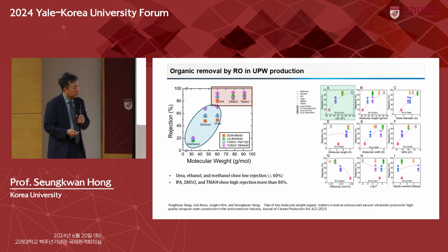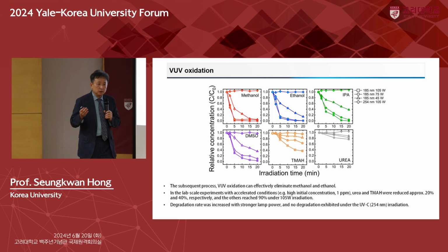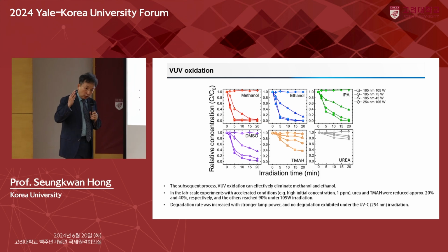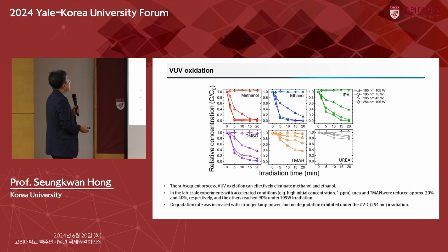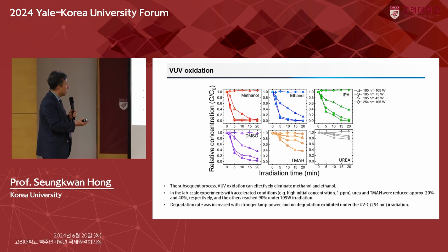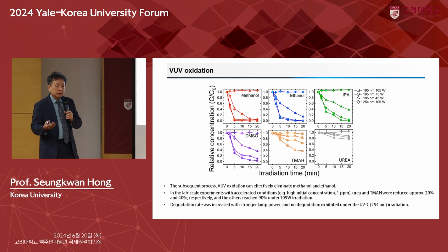So what do we need to do? We need to also use TOC UV. Vacuum UV should be applied to degrade these organic matters further. Are they working or not? Here's the result. For methanol, ethanol, IPA, and DMSO, at 185 nanometer and increasing intensity, we were able to degrade those organic matters. However, TMAH and urea, particularly, are not degraded by the vacuum UV in this UPW process.